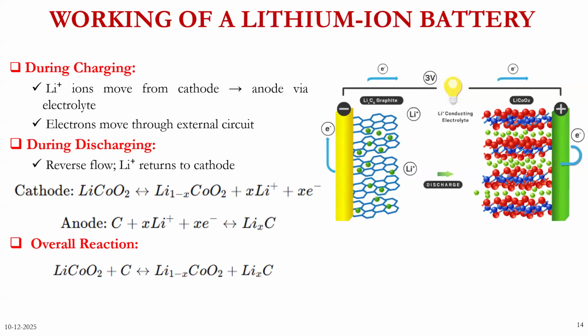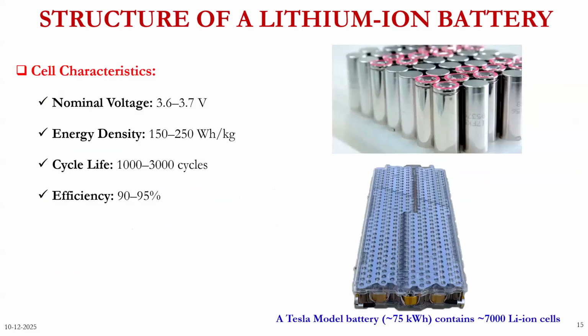Coming to the characteristics of a cell, the nominal voltage is 3.6 to 3.7 volts. Energy density is around 150 to 250 watt hour per kg. Another advantage of lithium ion batteries is their life cycle. The life cycle of a lithium ion battery is around 1000 to 3000 cycles, which is very high compared to lead acid batteries. And the efficiency of lithium ion batteries is also very high, approximately 90 to 95%. So 90 to 95% efficiency tells that whatever energy it gets charged with, it is almost able to deliver the complete energy.